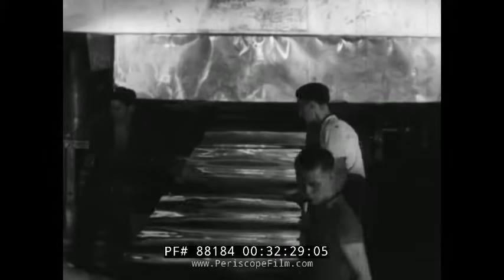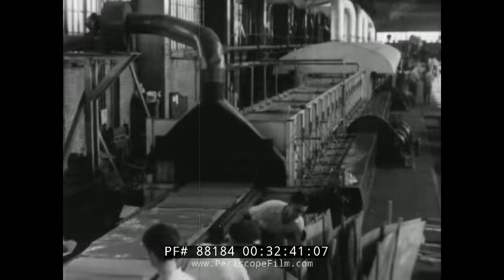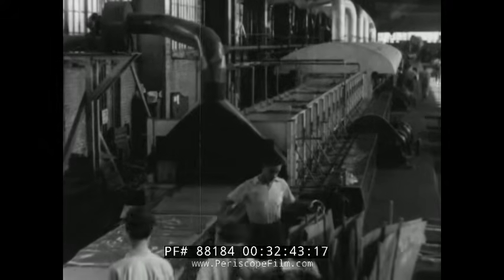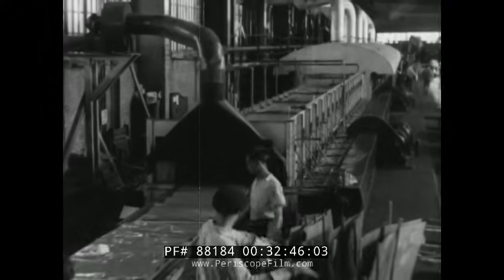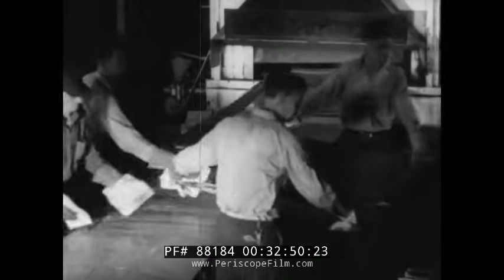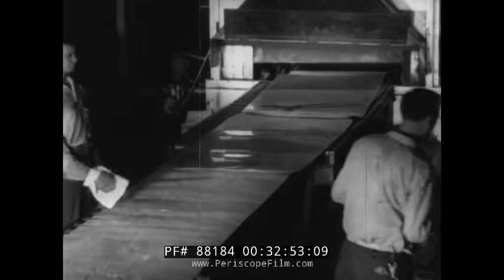Hot rolled sheets must go through a finishing process, the first step of which is annealing in a long, continuous furnace. Inside the furnace, combustion is carefully controlled. Having gone through the combustion chamber, which is followed by a cooling chamber, the sheets, now uniformly soft in temper, emerge at the discharge end of the furnace. The sheets are then pickled in acid and washed to clean and improve the surface.